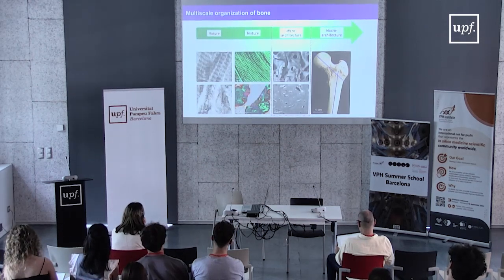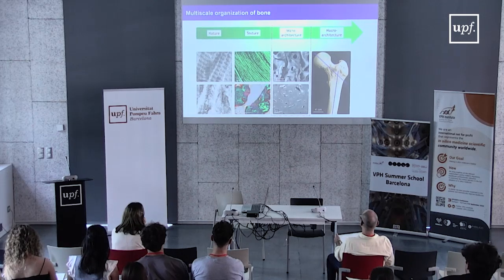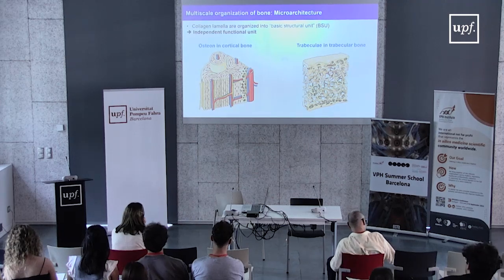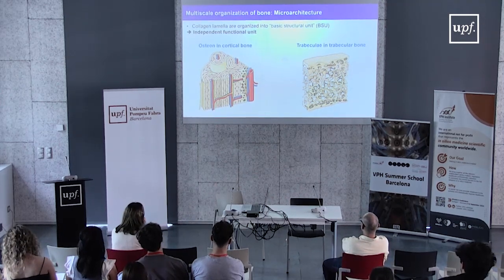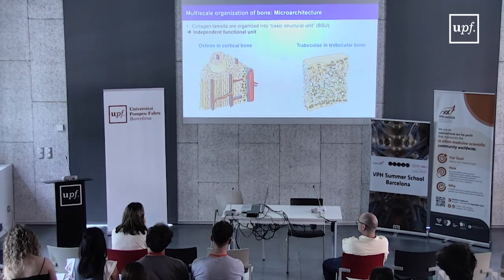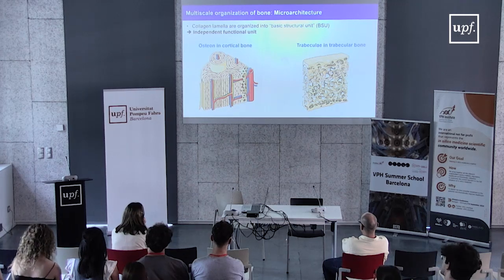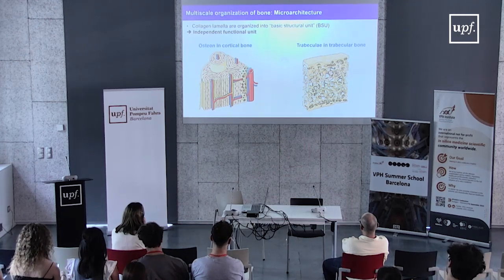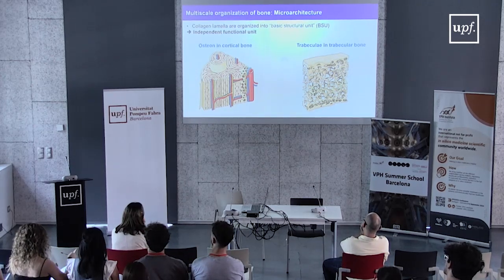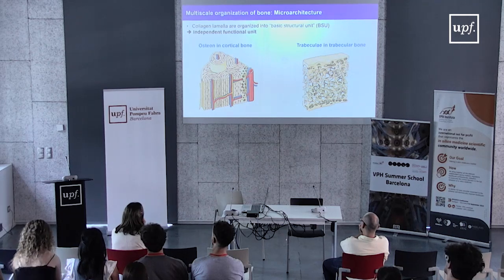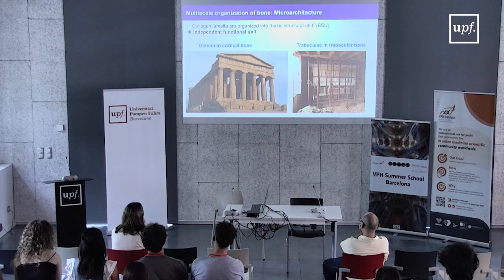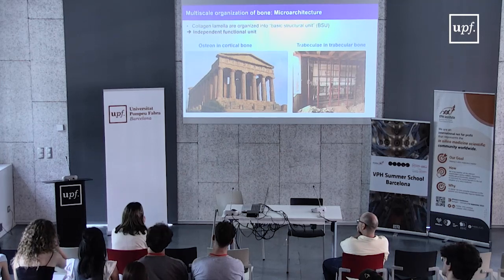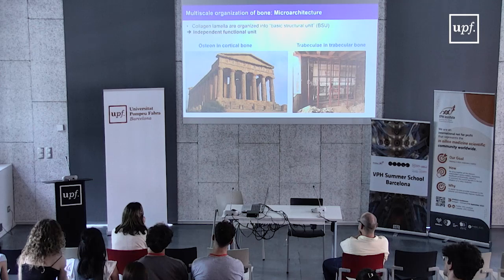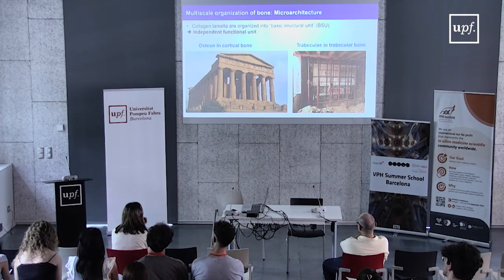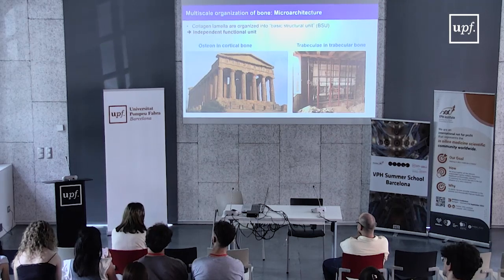The different collagen lamellae will compact and create the microarchitecture that we can find inside the bone. All the different lamellae will compact to form osteons in cortical bone, or will compact to form trabeculae in trabecular bone. Each osteon and each trabecula is a functional unit of the bone. An osteon or a trabecula is independent of the other trabeculae or osteons, and it's what we call the basic structural unit. In terms of structure, and it's what we consider as the geometry of the bone, the osteons can be seen like columns of dense compact bone, usually alongside the stress line. And trabeculae are more like a scaffold to limit the collapsing of the cortical bone.